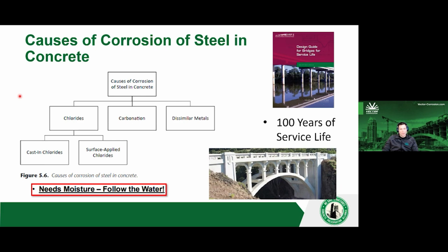The other way, and probably more likely for me in the Midwest, is de-icing salts applied to the surface throughout the winter. Things melt, and that melt-off just leaches through the porous nature of concrete, reaches the level of steel at a certain level, and corrosion can initiate. Now, if you're on the coast, that could be a marine environment. Saltwater is the same thing. Continual exposure to a marine environment can also build up chloride levels and break down the passivation layer.